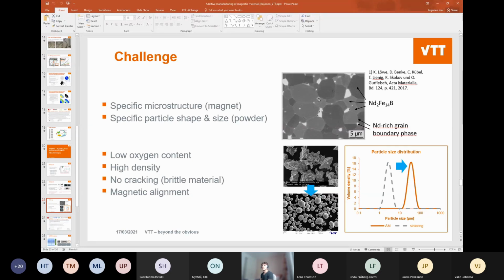And then the other challenge is that there isn't a powder commercially available that would have the proper powder particle size and shape. So we need spherical particles instead of the irregular shape that is used for the conventional sintering of these alloys today. And the same goes for the particle size distribution. In sintering you use a lot smaller particle size, and what we need to do is to shift the peak into an area which is usable for the laser powder bed fusion process, meaning that it is easily flowable, and you can spread the powder in a homogeneous way so that the process works. And the purpose of our project is to make such a powder which is spherical, which has the proper particle size distribution for the additive manufacturing process, and which also has an alloy composition in which we can reach the desired microstructure and the desired properties in the end.